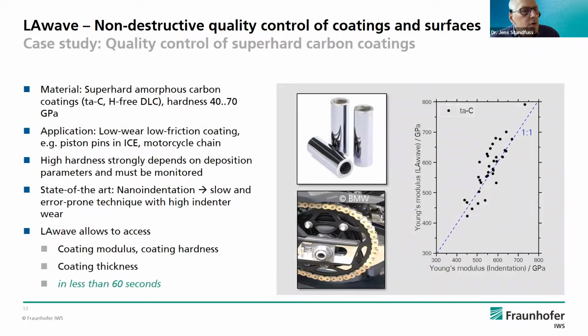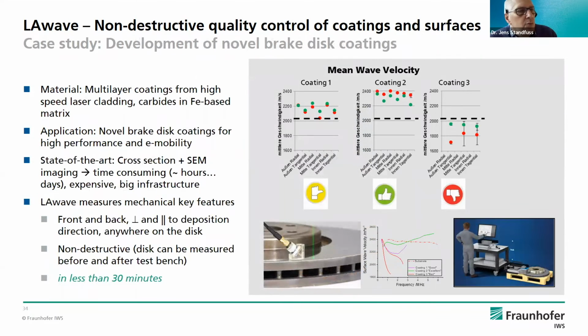Like shown here, for some DLC coating for chains used by BMW. The coating is done for chains to reduce the wear and also to lower the friction, and you get an effect of about 10%, something like this. And this is transferable to different things. You don't need state-of-the-art destructive testing and characterizations for this. And at the end of the day, you get some very interesting results, and this in a very short time.